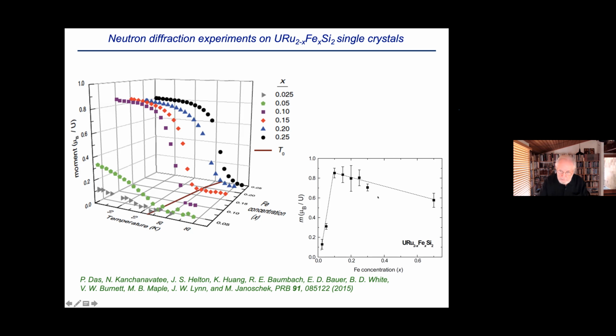Now this is measured at low temperatures, and bear in mind that the transition at higher temperatures close to the phase boundary actually occurs out here. So you might think there's a discrepancy between this hidden order transition composition and the one along the phase boundary, but it's simply due to the fact that the line between the hidden order and antiferromagnetic phases is not vertical, it actually has a slope.